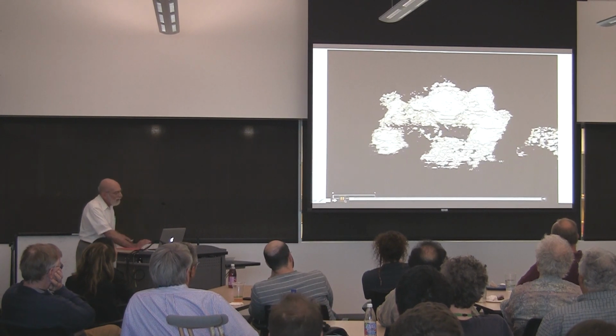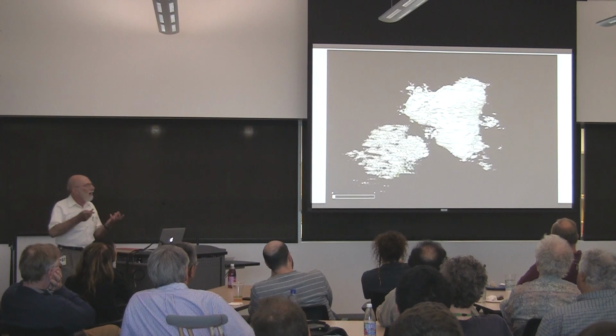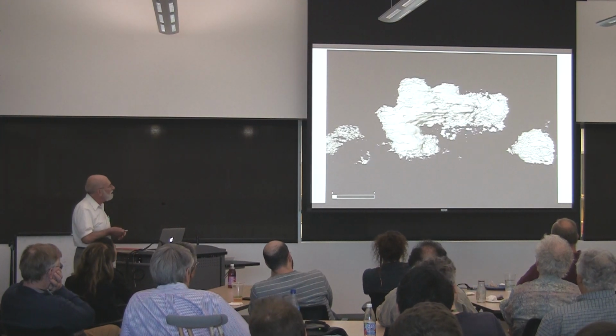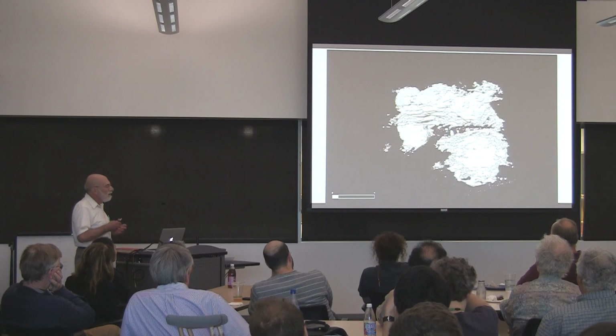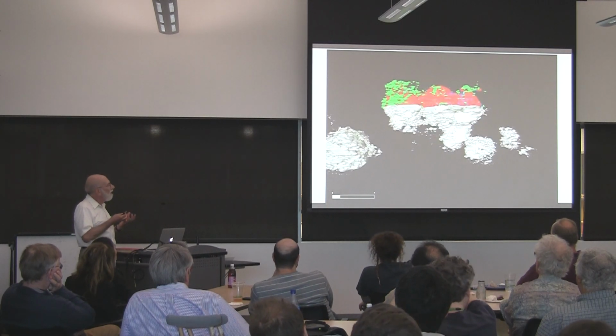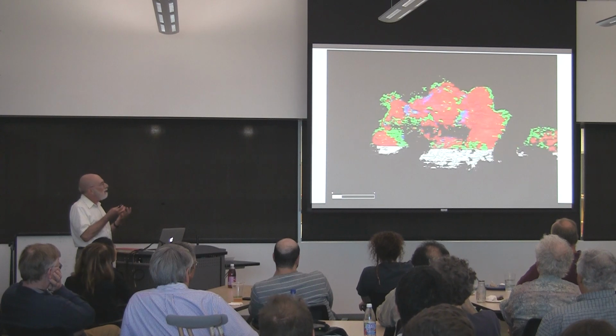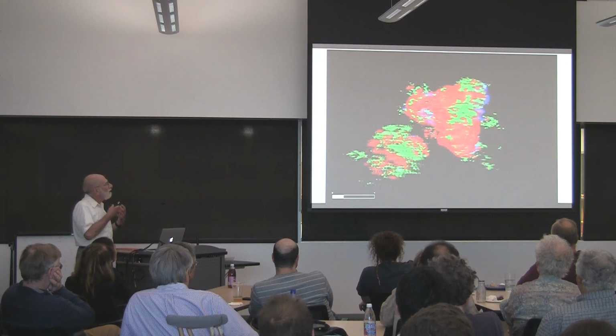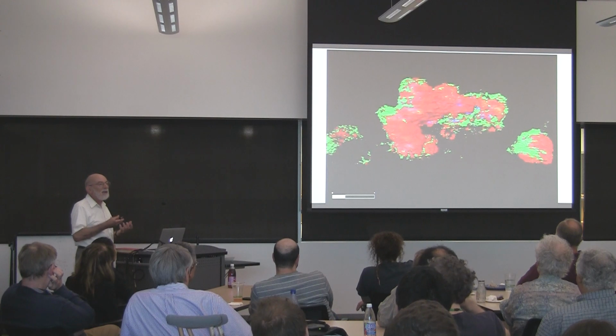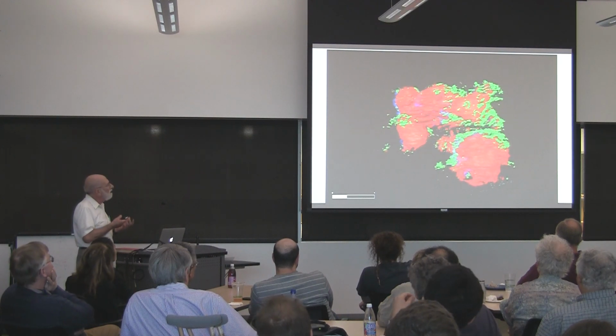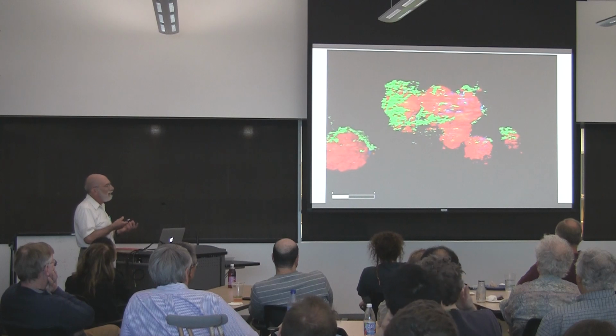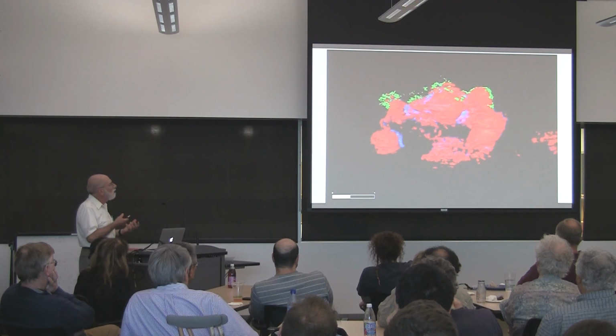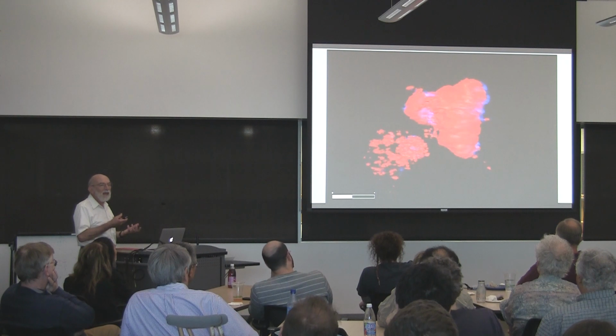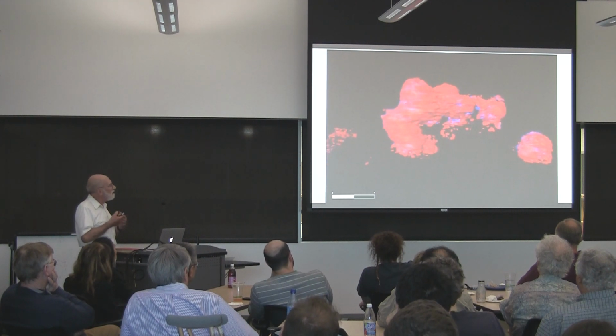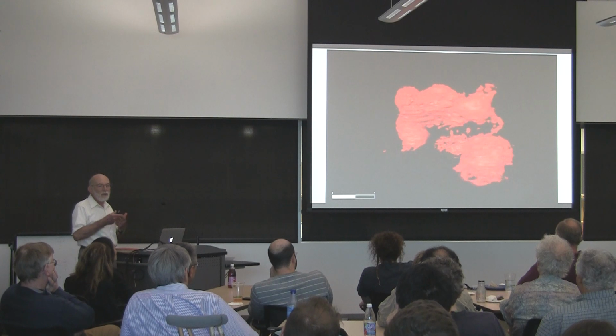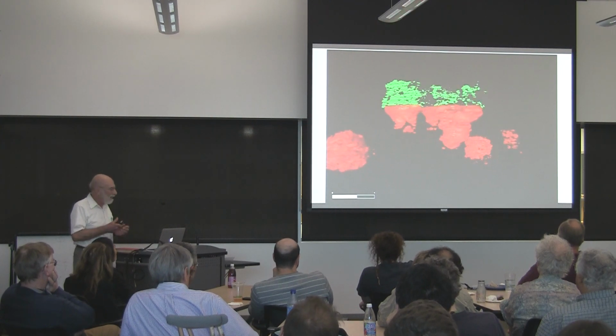me, is that you can take a tiny piece, this is probably about 5 microns across, you can take a tiny piece of this cathode material and do a tomographic reconstruction with chemical sensitivity, where again red is nickel oxide, green is metallic nickel, and blue is the mixed state. And so you can do this with significantly sub-micron resolution in 3 dimensions and with chemical sensitivity.